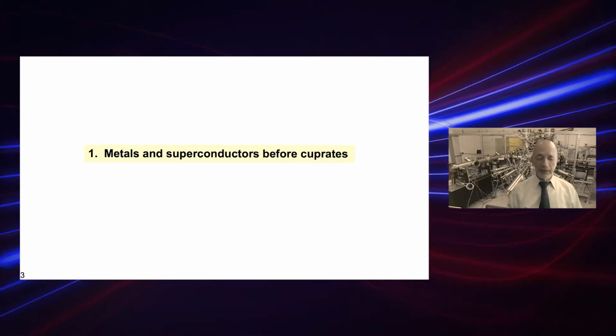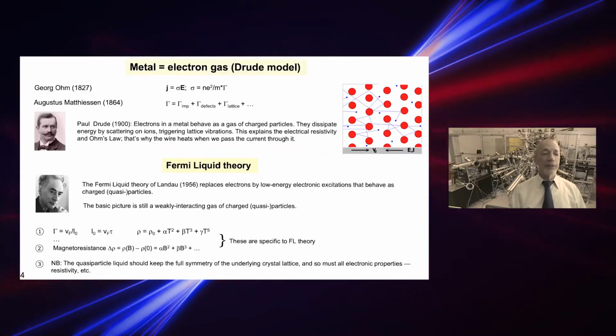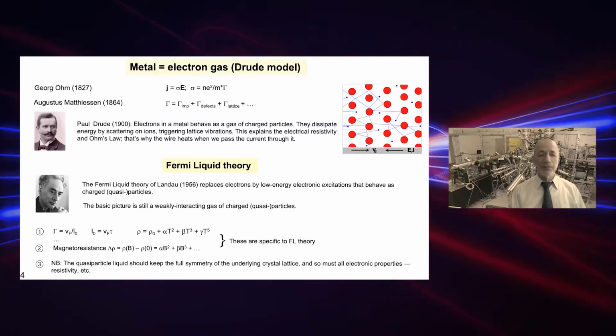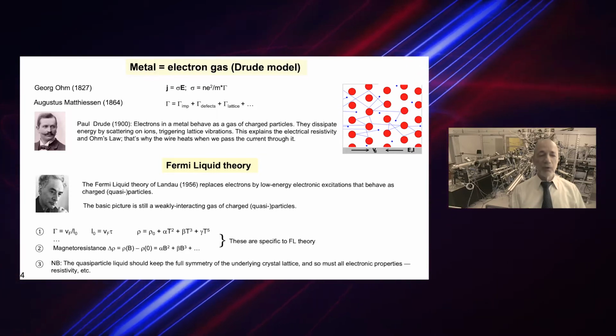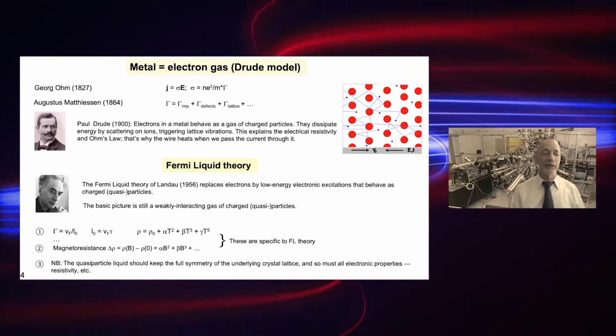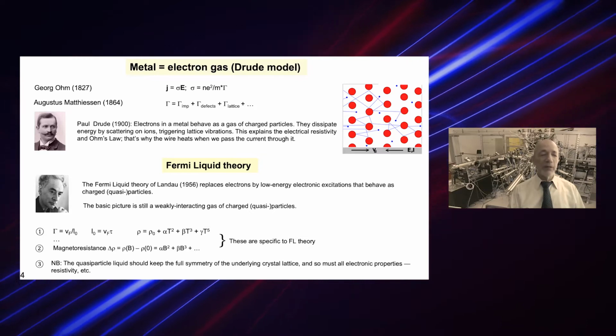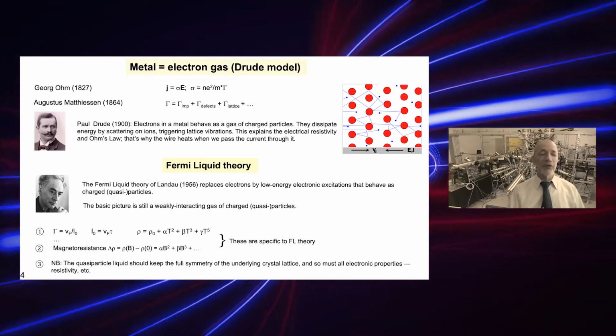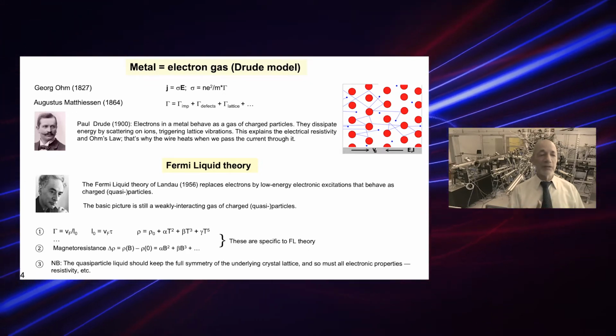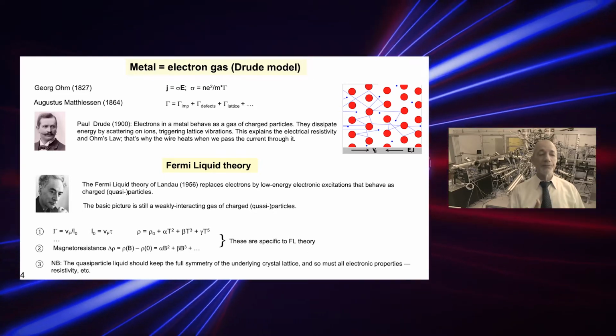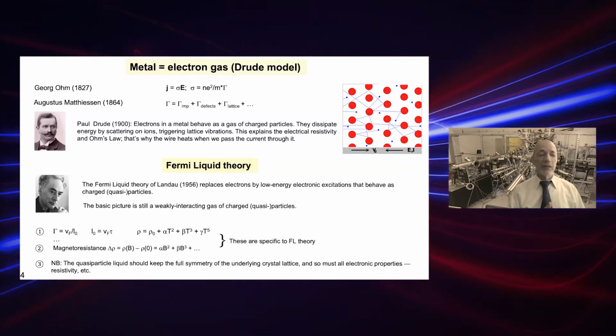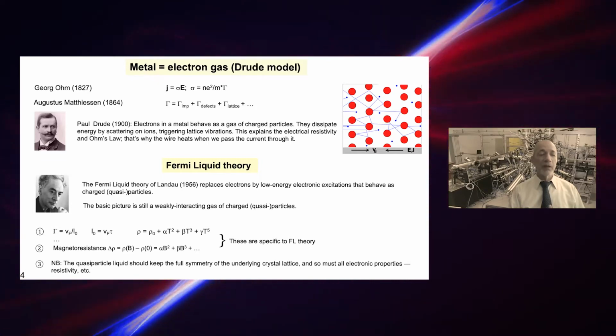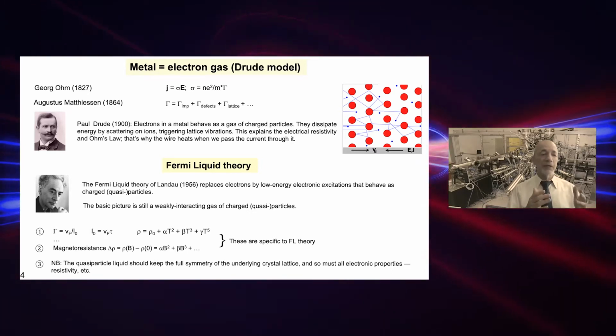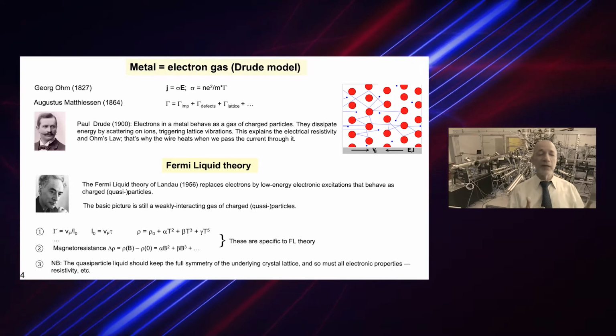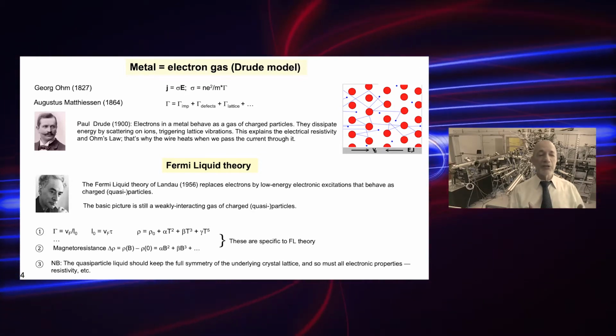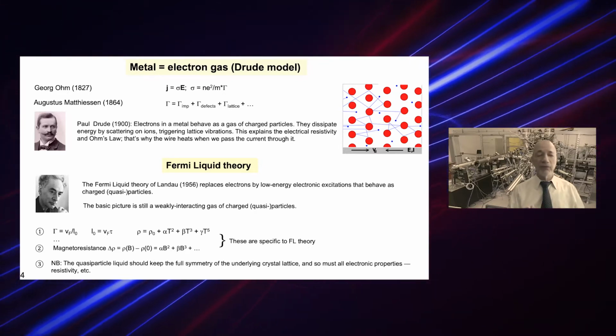So, a little bit of a glance back. The textbook chapter on metals was largely written by 4 authors. It was initiated by Paul Drude, who modeled metal as an electron gas contained in a can. This model was refined by Lorentz, quantified by Sommerfeld to account for the Fermi statistics, and finally put on firm theoretical grounds about 60 years ago by Landau, the so-called Fermi liquid theory. Here I have singled out a few details that will prove to be important in what will follow. They come from the existence of the Fermi surface. Because of that, only a small fraction of electrons, of the order of kT divided by the Fermi energy, is available for scattering. And the low energy excitations behave as a nearly ideal gas of effective quasi-particles.